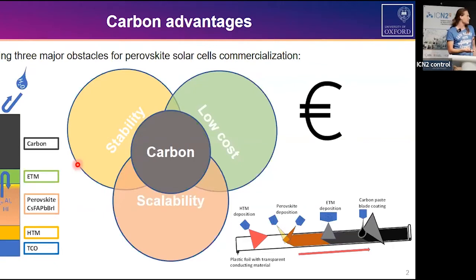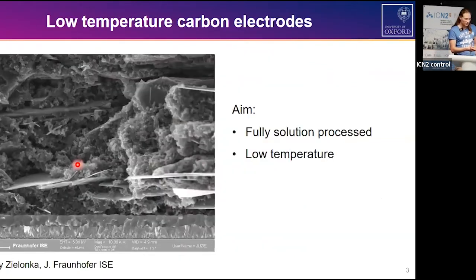And I hope having convinced you, I'll dive into one other detail. We are here at the Institute of Nanoscience and Nanotechnology, and some of you haven't worked with carbon electrodes before, but with metal electrodes. The metal electrode is usually several tens of nanometers in thickness. Just to give you an impression, this crystalline layer is the actual perovskite absorber, about half a micron thick. The carbon electrode itself is a rather thick film, in the tens of micrometers, extending out of this SEM cross section, just to give you an idea of the dimensions.